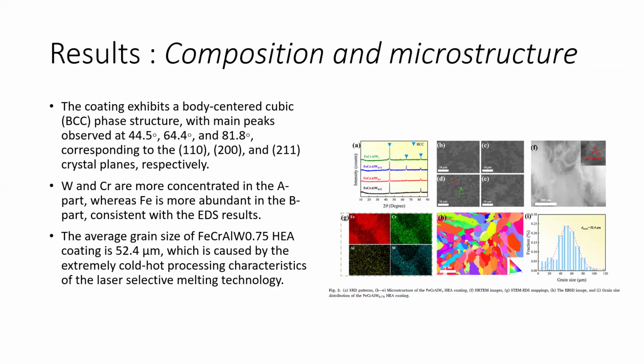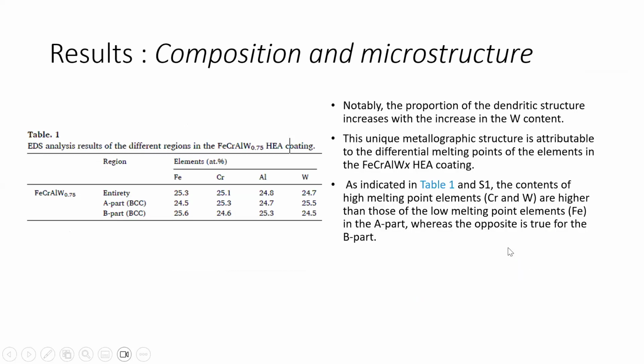Tungsten and chromium are more concentrated in the A part, whereas iron is more abundant in the B part, consistent with the EDS results. So the average grain size of the ferrochromium aluminum tungsten 0.75 coating is 52.4 micrometers, which is caused by the extremely rapid cooling and heating characteristic of the laser selective melting technology.